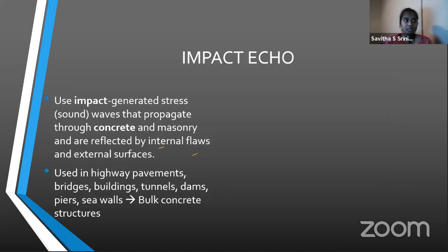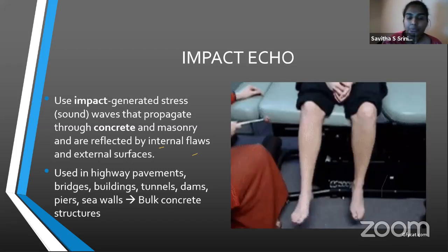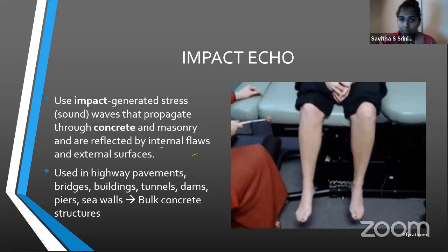The next method is impact echo. Again, impact echo is similar to ultrasonic pulse velocity, except that instead of using an ultrasonic pulse, an impact is generated using a sound wave. Think of it like a knee-jerk test where you knock something in order to get a response. This impact echo method is generally used in bulk concrete structures, whereas the ultrasonic pulse velocity method is generally used in smaller samples.